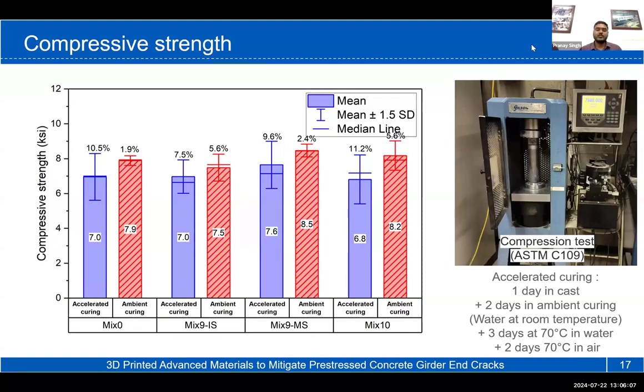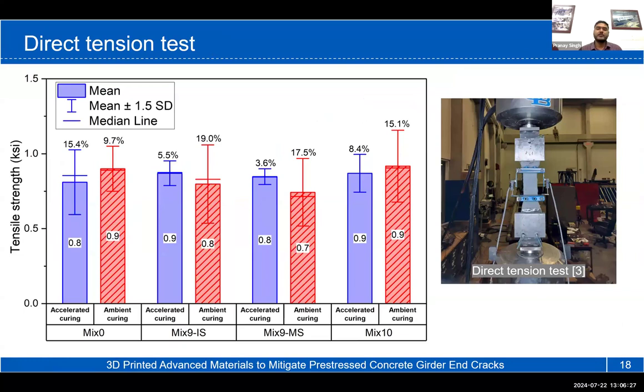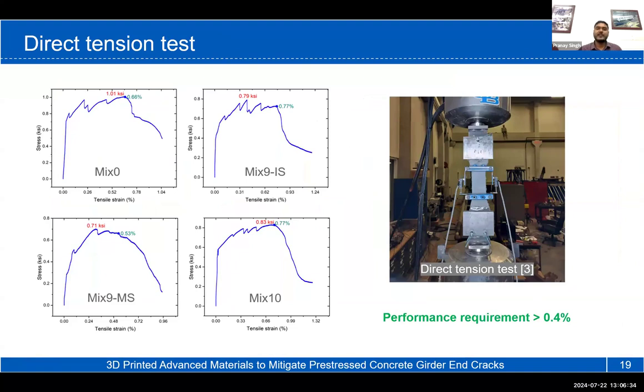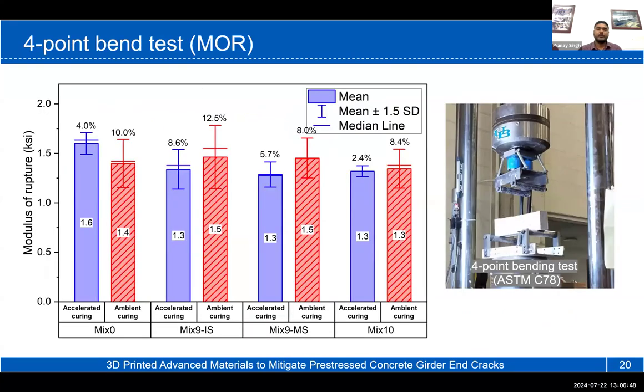The compressive strength results show that for all of the mixes that we are trying, we are getting a compressive strength in the range of around 7 to 8 KSI, and our initial target was 6 KSI for all these mixes. So we are getting the desirable compressive strength for all the 3 mixes. The tensile strength of these mixes is in the range of 0.7 to 0.9 KSI, and the tensile strain capacity was higher than the limit of 0.4%. We have done a 4-point bend test, and the modulus of rupture from that test is in the range of 1.5 KSI for all the 3 mixes.